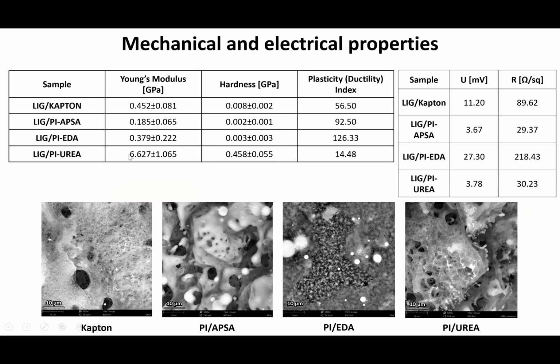Some of them have much higher Young's modulus. The hardness also, some of them are softer than on Kapton. Some of them are harder than on Kapton. Plasticity as well. In terms of sheet resistance, these are electrical properties shown on the right. Again, some of these samples perform better than Kapton. Others have higher sheet resistance, which is not so good for electronics, but it may be good for sensing.